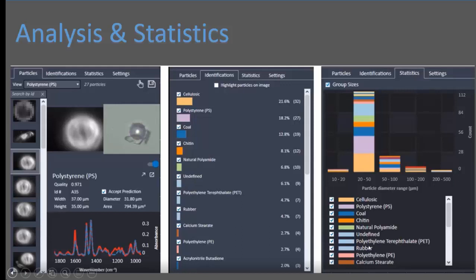Here's the most important part. For every particle that we've analyzed, you get an optical image, and then you get the infrared image, along with the spectrum and the reference spectrum overlaid. You also get the benefit of the diameter and area of the particle. This is something that EPA was very interested in for establishing what the co-contaminant loading may be on these particles. And so these were polystyrene particles.